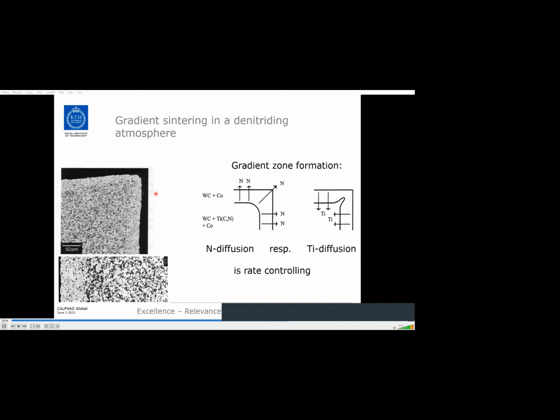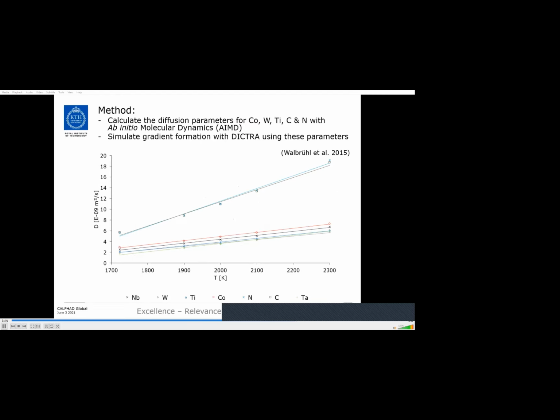So here is typically what it looked like. And you can see clearly here the gradient zone. So why does this gradient form when you sinter in a denitriding atmosphere? Well, what happens is that nitrogen diffuses out of the material because the atmosphere is denitriding. Now there is a strong attraction between nitrogen and titanium. So when nitrogen diffuses out, titanium diffuses inwards, where there still is a high nitrogen content. And that means that this reaction can be controlled either by nitrogen diffusion outwards or inwards titanium diffusion.